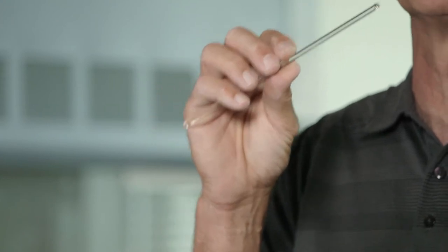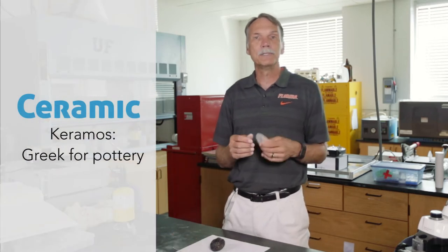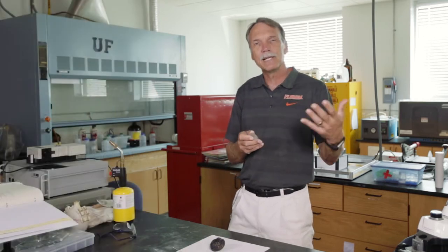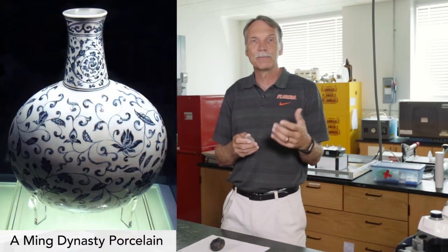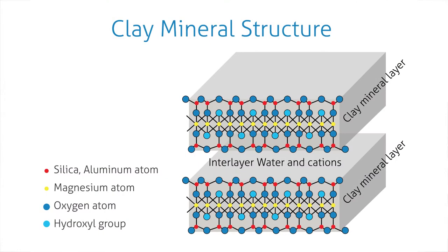The term ceramic comes from the Greek word 'keramos,' meaning pottery, which makes sense because the obvious early application was making pottery. We talked in the clay lecture about using kaolinite clay to form porcelain. Porcelain is the ceramic that forms when you fire kaolinite clay above 1000°C. As you fire it at very high temperatures, the water between the clay layers is driven off and the layers form a chemical bond — usually a bridging bond between silicon and oxygens across those layers — forming a new compound.